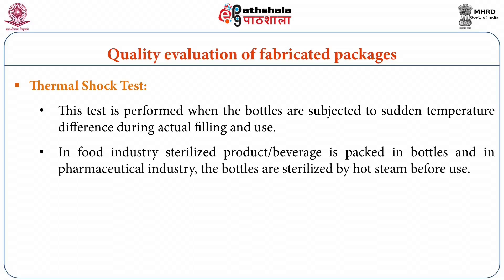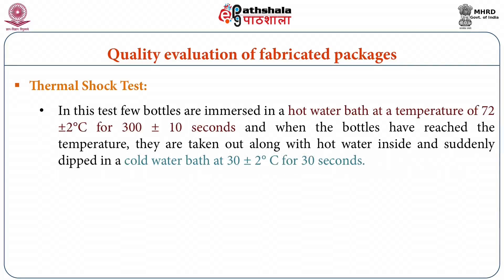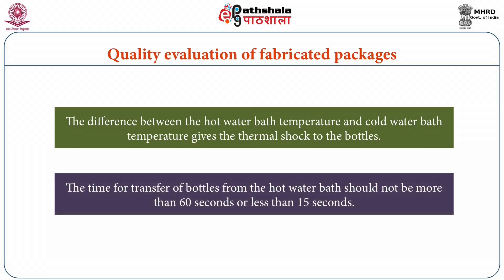The next test for bottles is the thermal shock test. This test is performed when the bottles are subjected to sudden temperature differences during actual filling and use. In the food industry, sterilized products or beverages are packed in bottles; in the pharmaceutical industry, bottles are sterilized by hot steam before use. In this test, bottles are immersed in a hot water bath at 72 ± 2 degrees centigrade for 300 ± 10 seconds, and when they have reached that temperature, they are taken out and suddenly dipped into a cold water bath at 30 ± 2 degrees centigrade for 30 seconds, after which the cracks developed are observed. The difference between the hot and cold water bath temperatures gives the thermal shock. The transfer time from the hot water bath should not be more than 60 seconds nor less than 15 seconds.